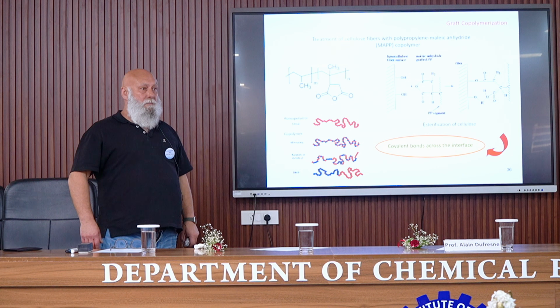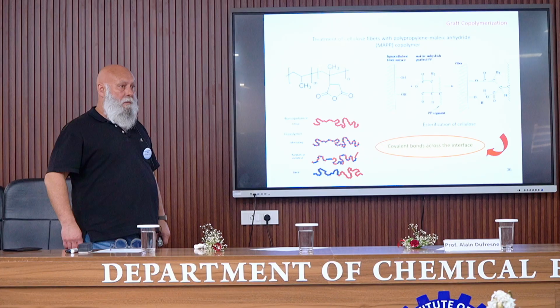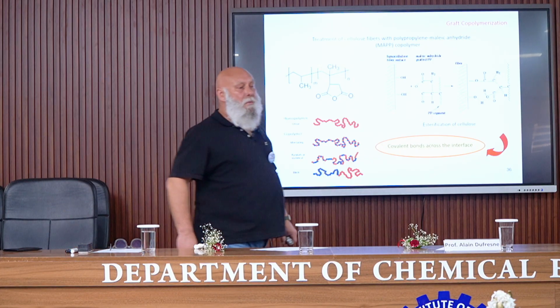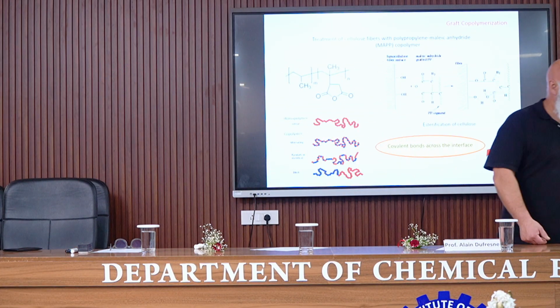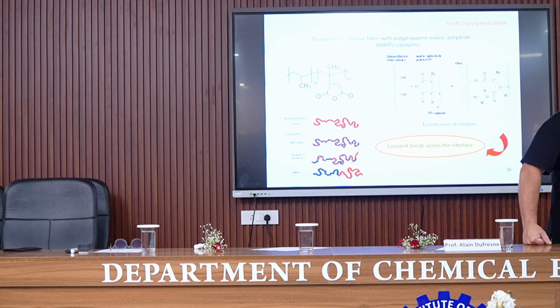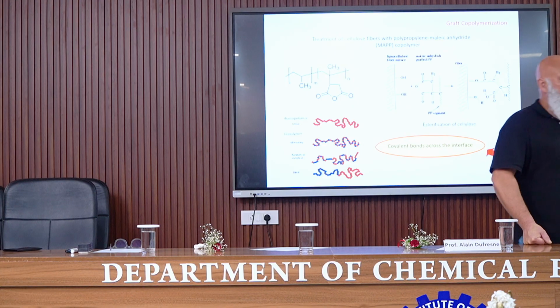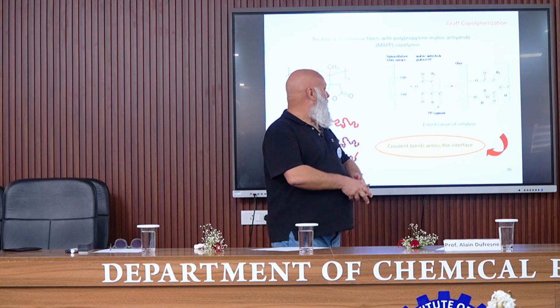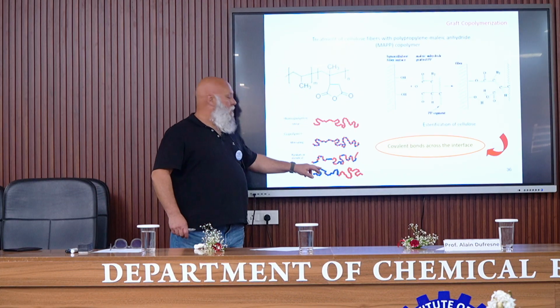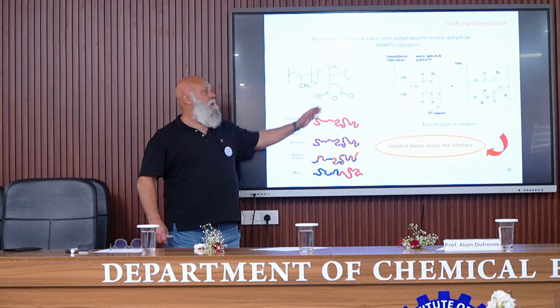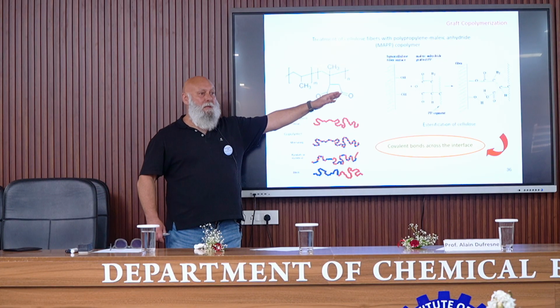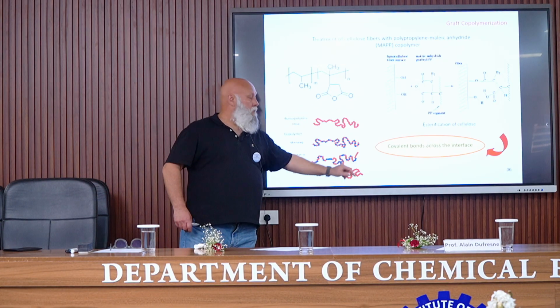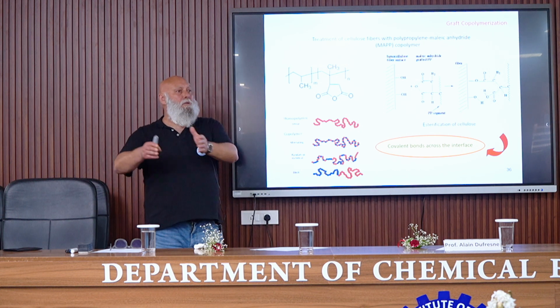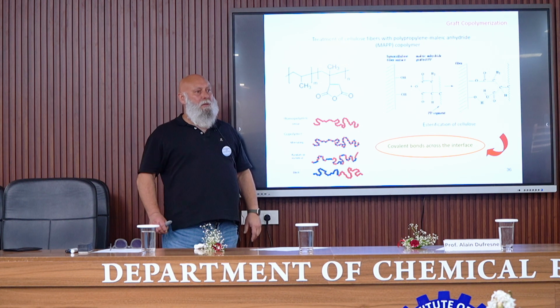How do you simulate this kind of study? What kind of software do you use for studying this kind of structure? You mean for the block copolymer? For the block copolymer, to have this compatibilizing effect, it's necessary to have a hydrophilic block that can interact with OH groups from the surface of the fibers. And the second block is generally the polymer that is used as a matrix.